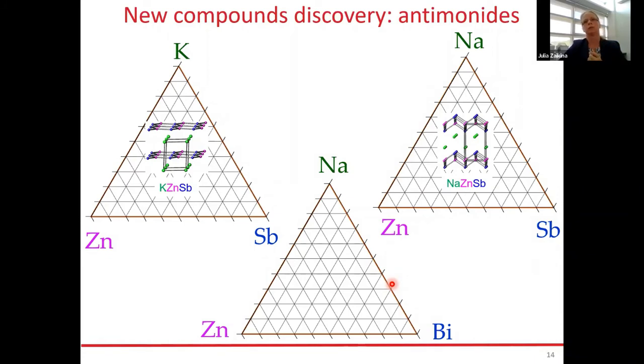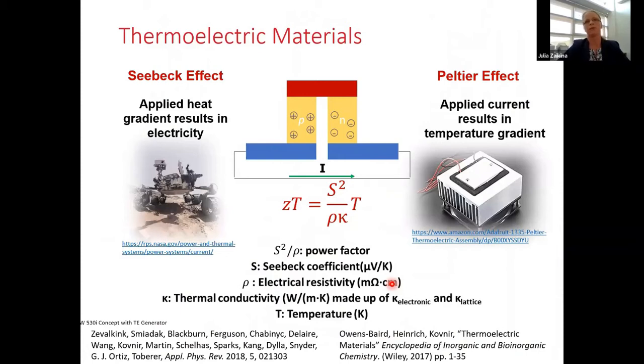But another reason to look into this system was that we hope to discover new thermoelectric materials, because in the literature there are several examples of antimonide compounds with complex crystal structures which do have high thermoelectric efficiency. For a good thermoelectric material, we want a material which is a good electrical conductor, so ideally a narrow gap semiconductor, but it's also a very poor thermal conductor, similar to glass. Having those two sort of contradictory properties in one compound constitutes the challenge of the discovery of new thermoelectric materials.